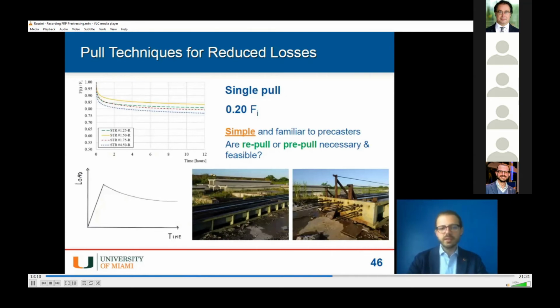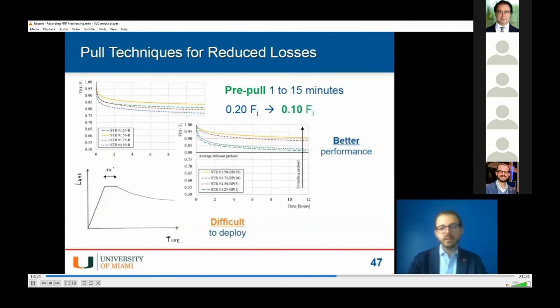The first solution that we tried is the one that I already mentioned. We just load our strand up to the level that we want, then we release it and we see how much losses we get, and that's 20%. That's too much, so we decided to maintain the load applied in load control before switching to displacement control for a while, from 1 minute to 15 minutes. We see that this solution is effective in reducing the level of losses that we have, but still it's not enough, and also it is a very difficult procedure to deploy in the field.